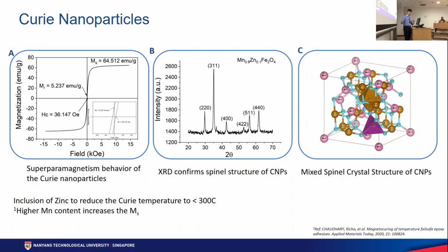heating temperature, we have to include non-magnetic zinc, so that we can decrease the Curie temperature to lower than 300 degrees. So when it reaches somewhere between 260, 270, it starts to shut off, because that's the Curie temperature, the threshold of application. And we can see that the nanoparticles have superparamagnetic behavior, spinel structure by XRD.